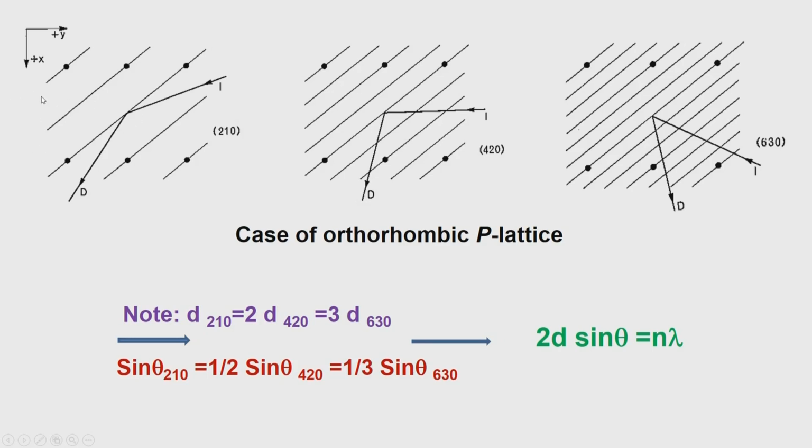So, when you do an X-ray diffraction experiment, you can get these intensities individually, because the angles are different. So, 2d sin theta equals lambda for all practical purposes, but when we deal with other issues like X-ray spectroscopy, for example, all the orders will appear together, and therefore we have to use the formula 2d sin theta equals n lambda. So, basically n can take different values, and that represents the so-called order of the reflections.